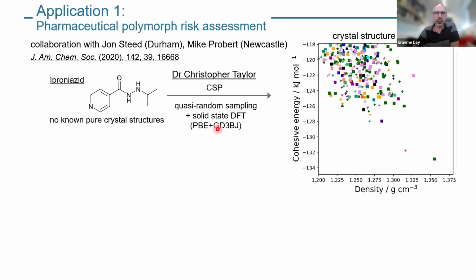Chris Taylor, a postdoc in my group, did the crystal structure prediction with that low discrepancy sampling and calculating energies with an accurate method here, solid state density functional theory. And this is an example of a crystal structure prediction landscape. So each of the points on this landscape represents the density and the energy of a different crystal structure of that molecule. Here, the symbols and colors just correspond to different space groups, which isn't important for us now. So you can see there are a few low-lying structures, and we hope that those are the ones that we find when we do experiments.